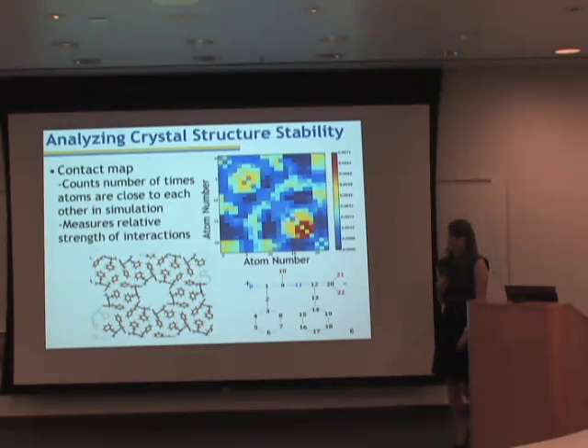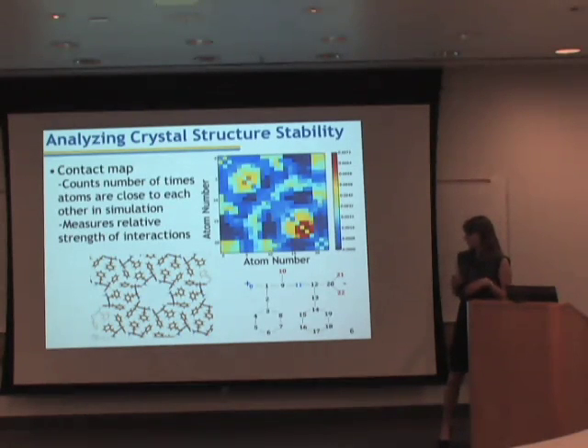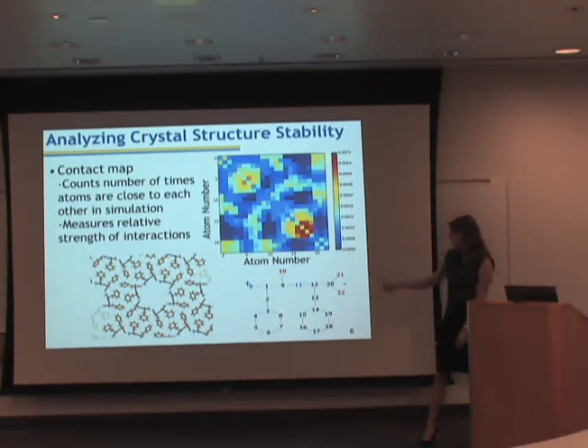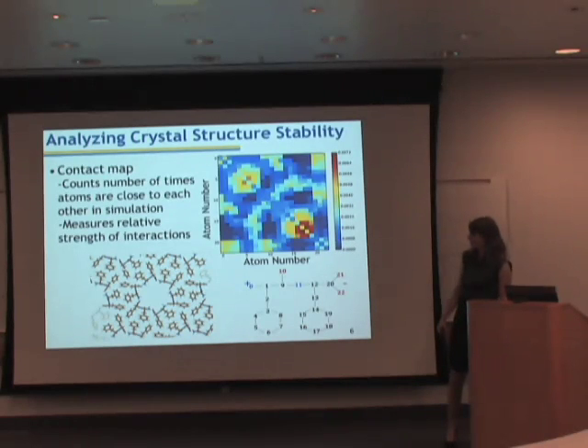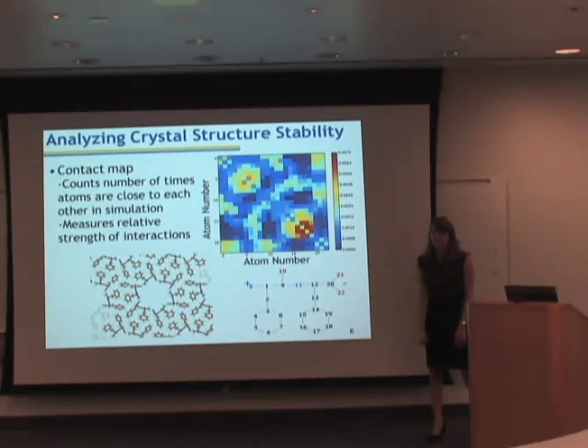Another way we can look at the results of our simulations is using a contact map. A contact map is made by comparing all possible peptide pairs in the system and counting the number of times non-hydrogen atoms come close to each other in the simulation. In this way, we can get a quantitative metric of the strength of relative interactions between different atoms on interacting peptides. When looking at this contact map, the axes here on the left and bottom are labeled with numbers that correspond to atom numbers on this representation of the diphenylalanine peptide below.